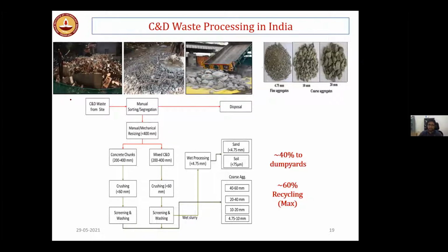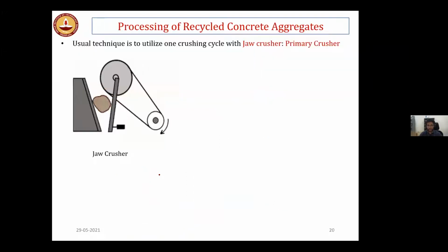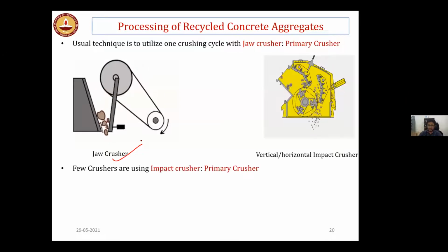So normally in India, what is happening? The C&D waste goes to the plant where they resize it. Resizing means they use some crusher to crush the aggregate into different sizes: coarse aggregate 60 mm, coarse aggregate 40 mm, sand particles. Some plants use dry crushing. Some plants use wet crushing in order to reduce the powder content, because some powder is emitted during the crushing operation. So normally only one crusher is being used at the site, that is the jaw crusher. And we have seen that some plants use the impact crusher.